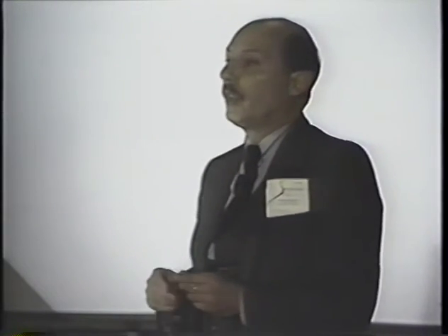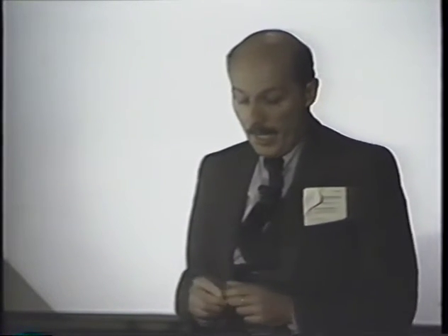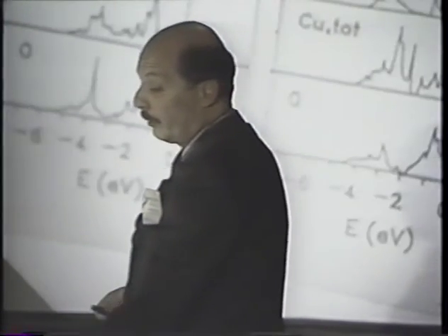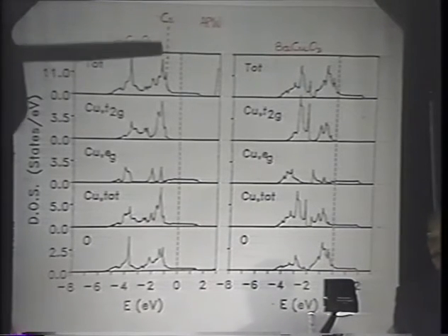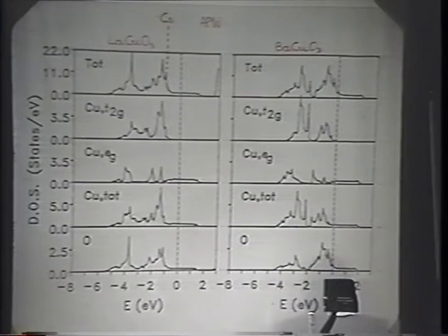We have taken the point of view that we can propose a model of the cubic perovskites as well in order to make a series of systematic studies. And we have seen that the cubic perovskite, which apparently is the building block of all these layered compounds, has a band structure and density of states which is quite similar to the layered ones. And you can see here a set of densities of states for the cubic compounds. What I have marked here is where cesium would be.